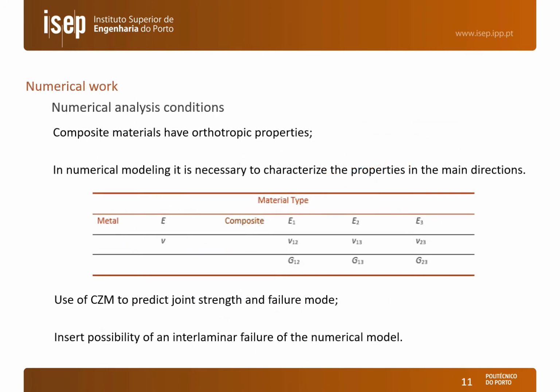The numerical work consisted of using cohesive zone modeling for strength prediction of the step lap joints. And as I said, the composite materials were modeled as orthotropic, and with this purpose we need the properties that are presented in this table. For metal we are considering only an isotropic material, but for composite we have to consider the different properties along the three orthogonal directions. We used CZM with a triangular law to predict the joint strength and the failure modes, and we included in the models the possibility of interlaminar failures at several locations along the joint.